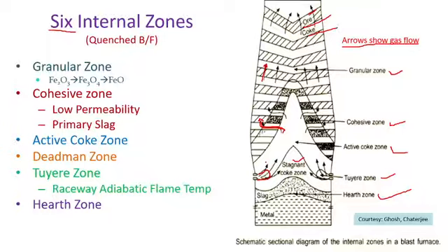Okay, so the burden descends. The combustion zone is in the form of a pear shape called the raceway, in which the hot gases rotate at high speed carrying a small amount of burning coke in suspension. In this pear-shaped raceway, there are burning cokes which swirl inside the raceway till they are converted to ash.